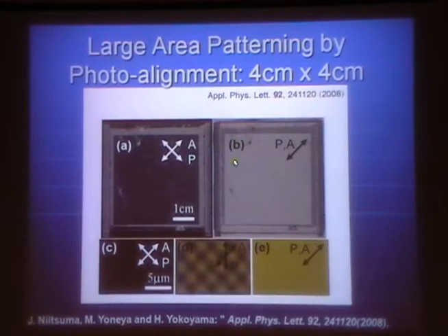So this is the prototype we made. It's already 5 years ago, and it is 4 centimeter by 4 centimeter, and the domain size is 1 to 2 micrometer. And still it contains lots of defects because we didn't use a clean room facility, but just an ordinary room can create this many defects.